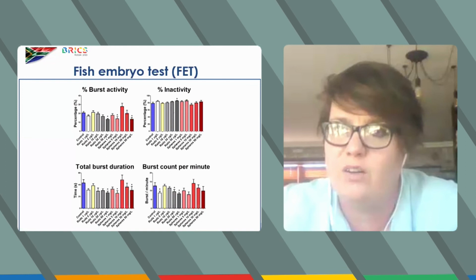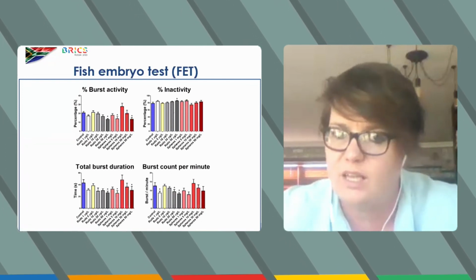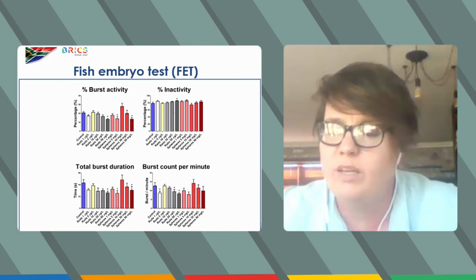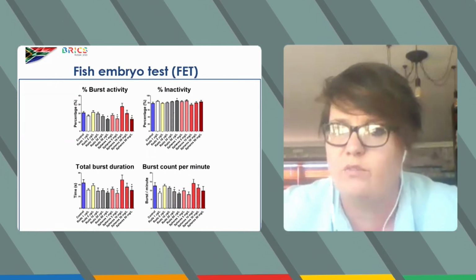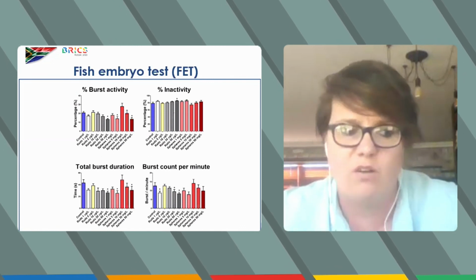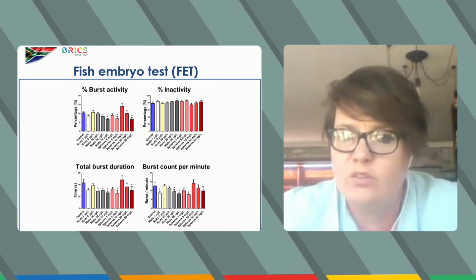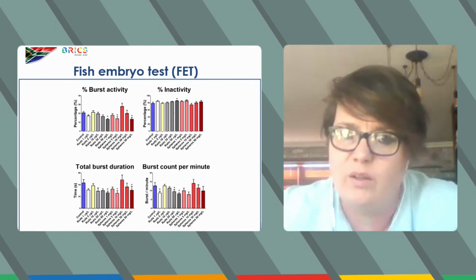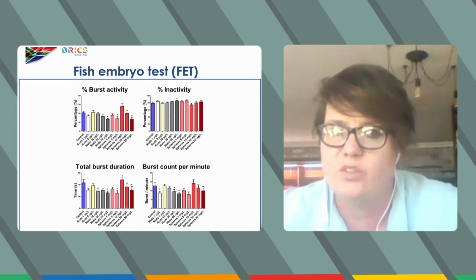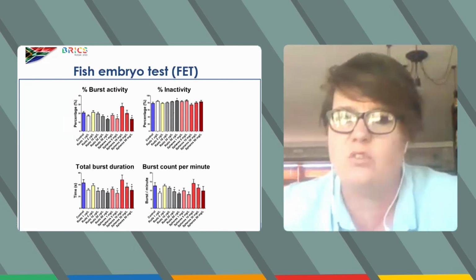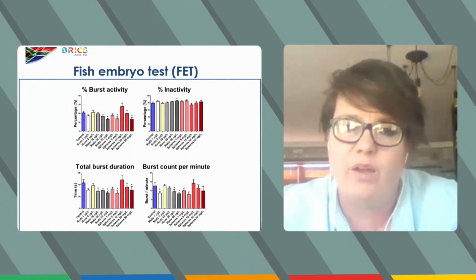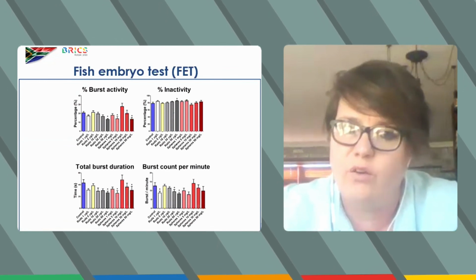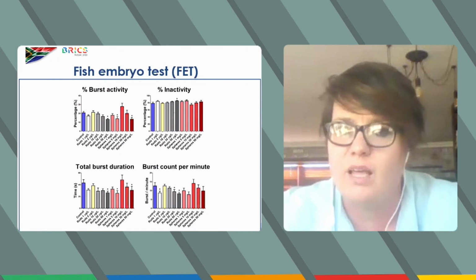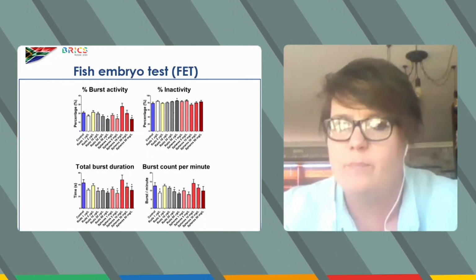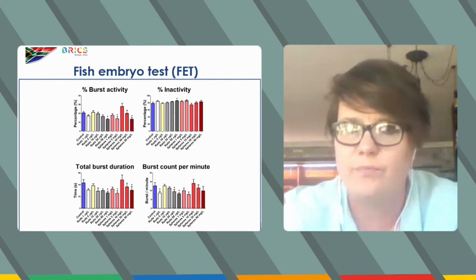However, the percentage increase in inactivity, that being the embryo just sat still within the chorion, and this movement is important for development of the fish, as well as the fish being able to break out of the chorion at the end of its growth period. However, what we did notice then, the spheres group actually is the one that decreased the total burst duration. So that would be the fish generally would have a burst, but if that duration is decreased, then it's almost a count of overexertion. However, with the rods group, we then noticed that there was a decrease in the burst counts per minute, that being the fish didn't even attempt to move. In other cases, they might move, but not as long.